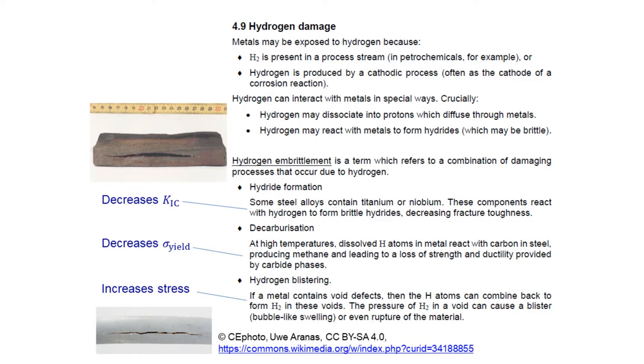Above about 150°C there is a good driving force for hydrogen to come out of solution from a metal. If an alloy has been treated with acid during manufacture and may contain residual dissolved hydrogen, it can be annealed before entering service to drive out this hydrogen. However, this is only effective for internally dissolved hydrogen from manufacture — it does not help against external hydrogen added in service from hydrocarbon streams or aqueous environments.